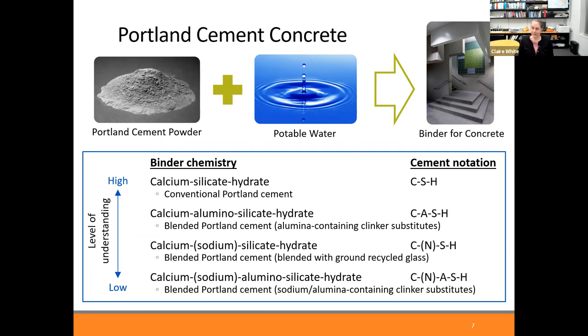So what happens when you make concrete? Well, you mix Portland cement powder with water. And I say potable water because you can't use briny salt water. And then we mix it with sand and other aggregates, larger aggregates, and then you get concrete. Now, there are many phases that exist in this cement powder. There are actually four main phases that, when you react them with water, create four more phases. And it's quite a complex system in terms of what's going on at what time. However, it is known that the main phase that gives concrete strength is called calcium silicate hydrate gel.